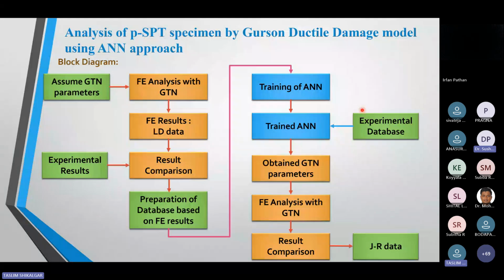So here I got these GTN parameters for the experimental database, and from these GTN parameters, I again performed some FE analysis. I compared my results with the experimental database, and from this I generated one J-R data with the help of this damage mechanics model.